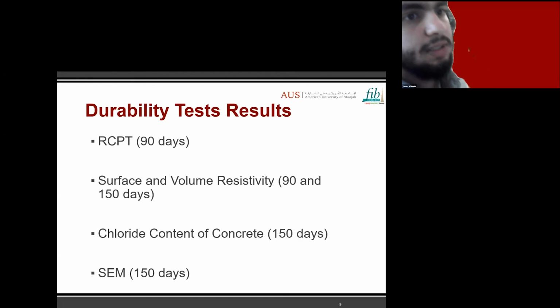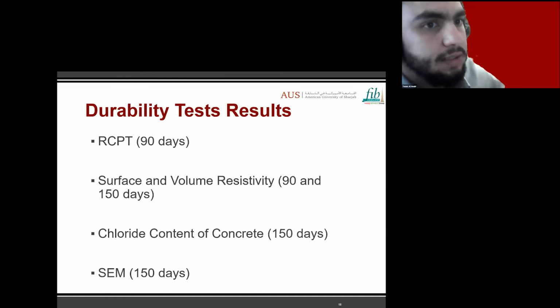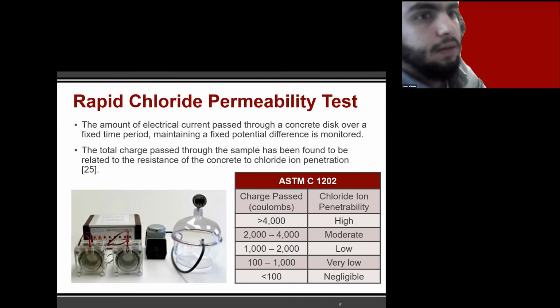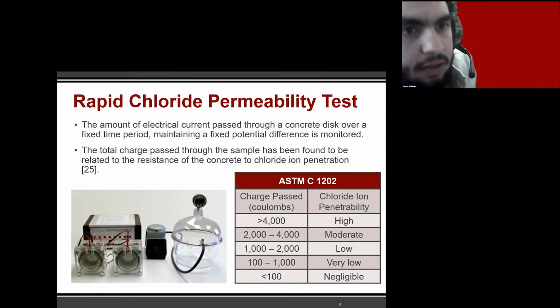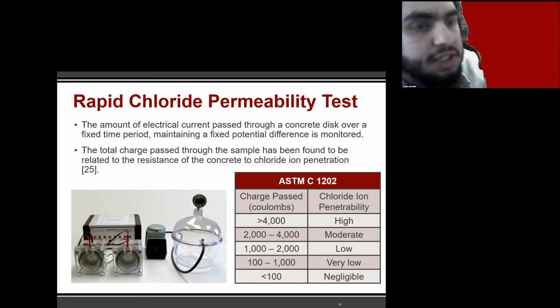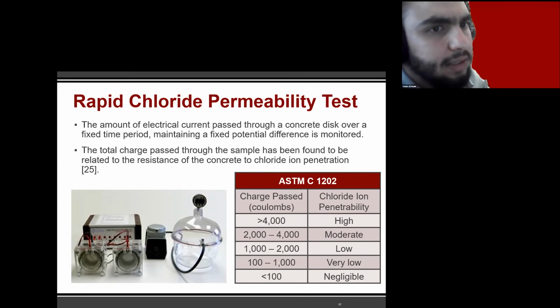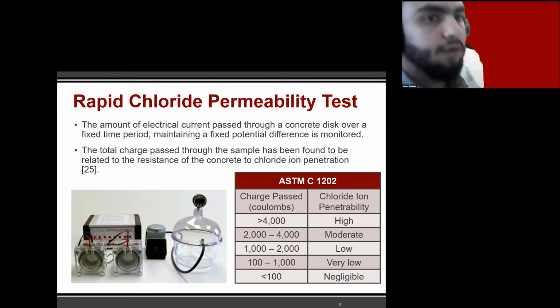Moving to the durability tests, which are the focus of this study. The tests performed include the RCPT test, the surface and volume resistivity test, the chloride content test, and the SEM. The RCPT test measures the concrete's ability to resist chloride ion penetration and thus provides an indication of the concrete durability. Following the ASTM standards, the RCPT test is performed on a small disc specimen with a diameter of 100 millimeter and a thickness of 50 millimeter.